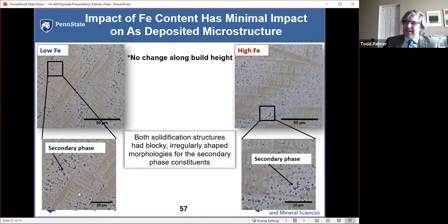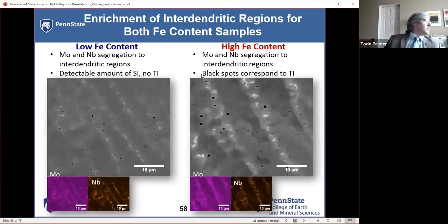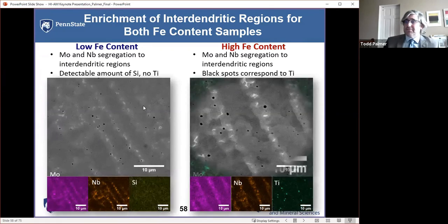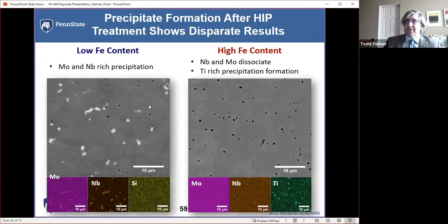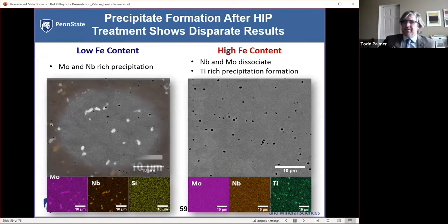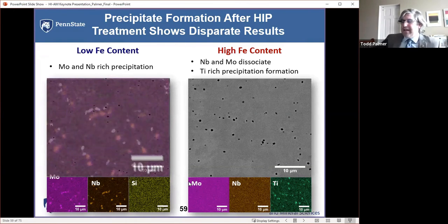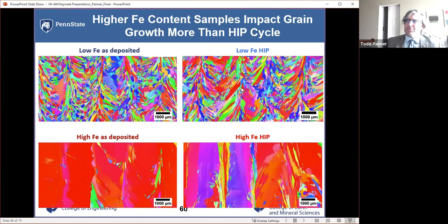And if you look closely at them, they're not the same. They're a little different. What we tended to see with low iron content is differences in the chemistries. The low iron was rich in molybdenum and niobium, which indicated the idea of a Laves-based phase, but our high iron content became rich in titanium. So there was a higher amount of titanium. These were really titanium-rich precipitates.